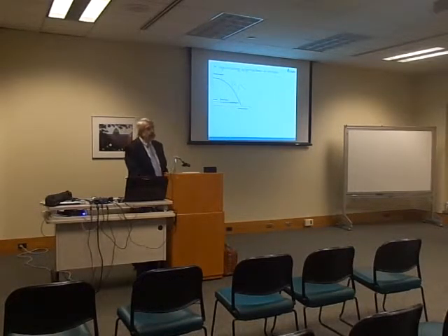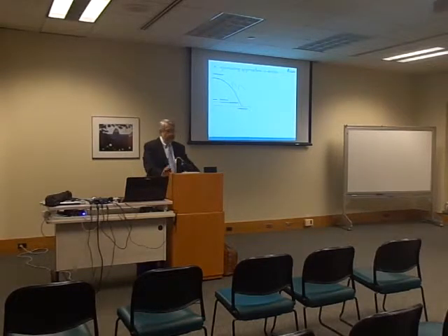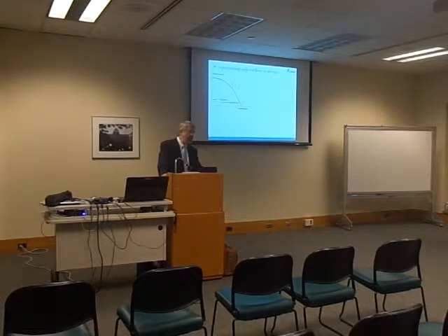I have two questions, very close to you, by the way. My first one was, what percentage rejuvenator did you use for your field applications? Yeah, the best that I know of, with 5%, you can get what you will get with between 25 and 30 of another rejuvenator. So one of the better products, it was 5%, that brought me back to the original stiffness. And your percent is based on the weight of the binder? It's percentage binders, yeah, I was showing binders. I skipped, if you notice, the mortar stuff.